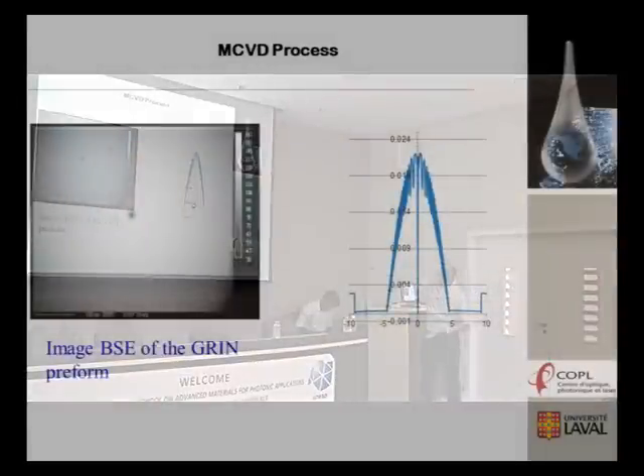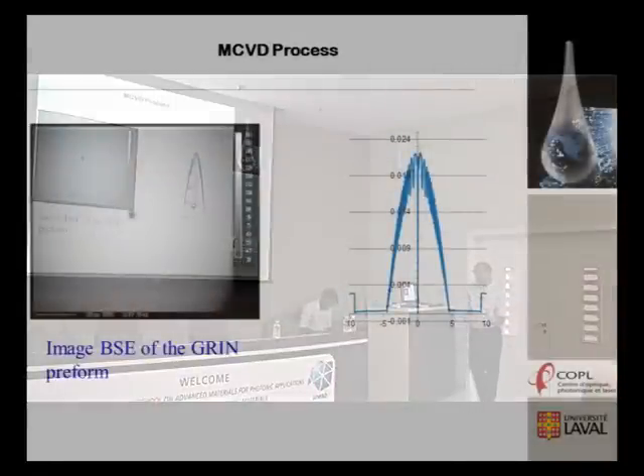Just to give an image of backscattering electrons for the inside, this is a profile of the different layers of the core of a GRIN preform. You can see each layer you deposit. We can see clearly the homogeneity of this layer in the way to control the behavior of this process. And at the end, we measure the profile of the refractive index to show clearly if we really reach what we are looking for, the difference of refractive index, and also the difference of the core. This is a monomode fiber with 9 microns of core and 125 of cladding.